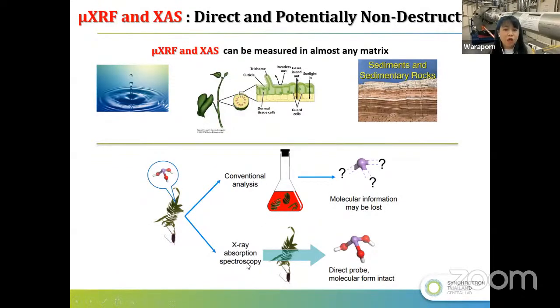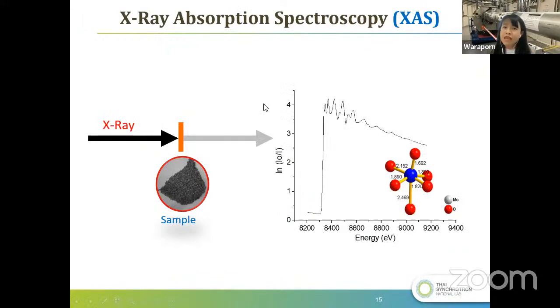But if you use X-ray absorption spectroscopy, you can see the speciation of the element in your sample, what kind of compound this element forms, and how it binds to the other elements nearby. For X-ray absorption spectroscopy, we shine incident X-rays onto the sample, and we get the signal. This is the spectrum. The first information we can get is called X-ray absorption near edge structure. This can give you the information on the oxidation state of your sample.